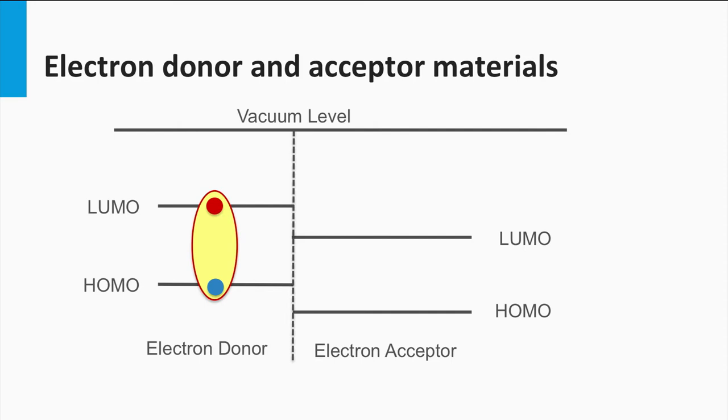In organic materials this is not the case. Light excitation results in so-called excitons, which are excited electron and hole pairs which are still bound and strained due to the mutual Coulombic force between the particles. The exciton can diffuse through the material. These excitons have a low lifetime in organic materials. They recombine back to the ground state within a few nanoseconds, meaning that the diffusion length of such excitons is in the order of only 10 nm.